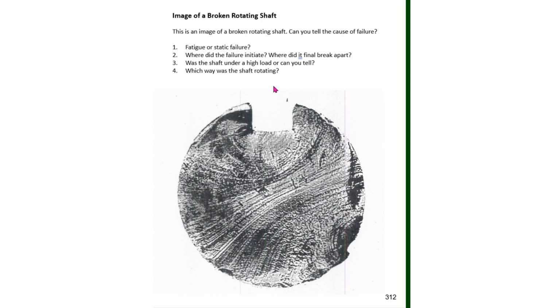To look at whether this was a fatigue or a static failure, we can look at this surface and see that it was fatigue. And the reason why is because in a fatigue analysis, we get these striations, or what are commonly referred to as beach marks. And they're simply lines that you can see in the failure plane. And what happens in a fatigue analysis is a crack is initiated and then it propagates. Every time this shaft makes a cycle, that crack opens a little bit more and then closes. And each one of those openings causes one of these beach marks.